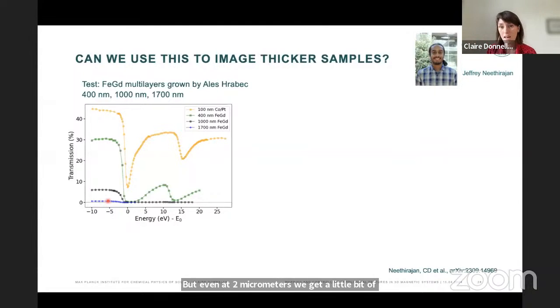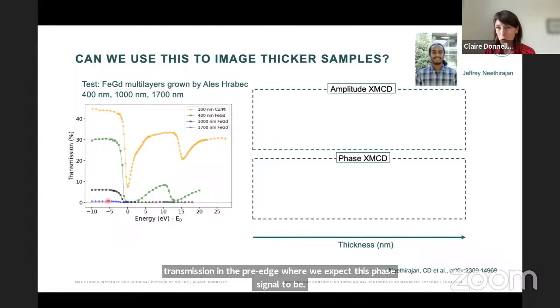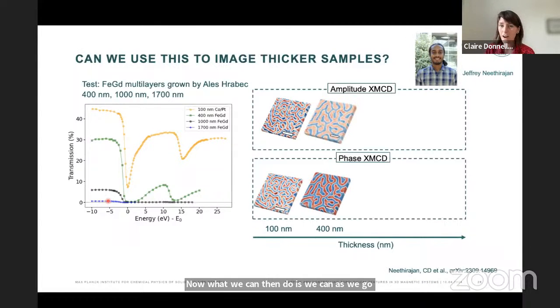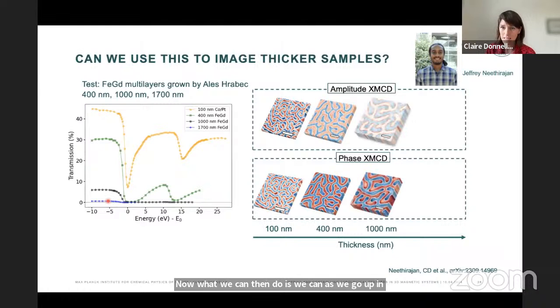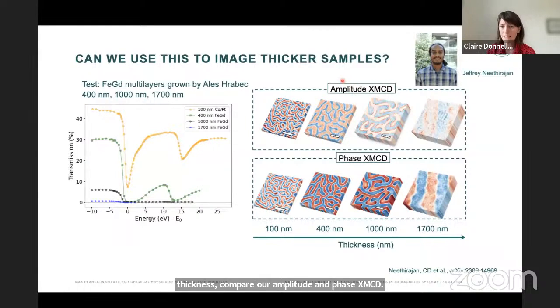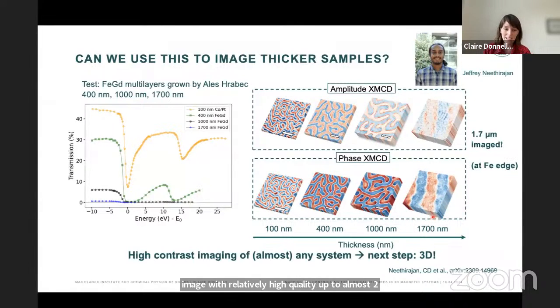Now, as we go up in thickness, we can compare our amplitude and phase XMCD, the amplitude essentially being our absorption contrast. We can see that the amplitude signal we lose pretty quickly as we go to thick systems, whereas with our phase signal we can image with relatively high quality up to almost 2 micrometers worth of material.